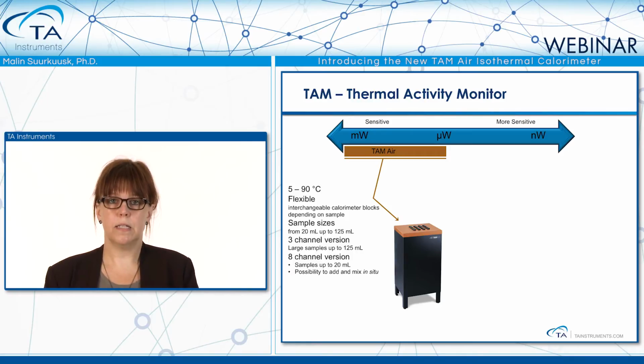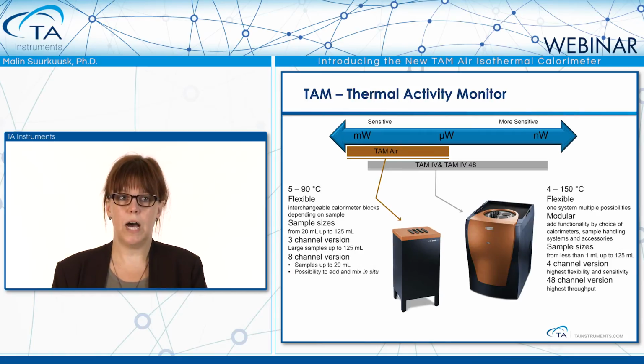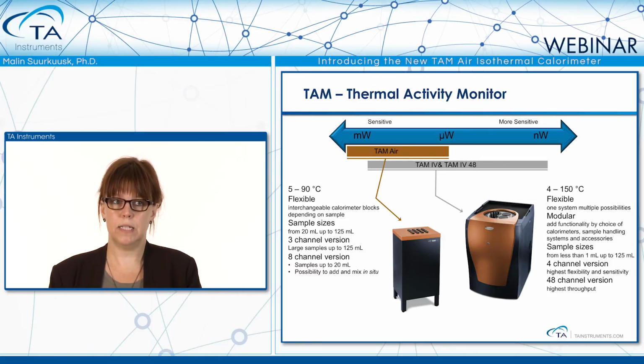But for some applications, the sensitivity of the TAM Air is not enough. Then we do also have the TAM 4. It's the more flexible calorimeter. It has much more sensitivity. It goes over the whole sensitivity range, back to nanowatt sensitivity. And this is a completely modular system that you can build up to your own needs, from very small samples below 1 milliliter up to 125 milliliter samples in this case. So depending on the needs, there is the TAM Air, which is perfect for cement and concrete and food applications. If more sensitivity is needed, there is also the TAM 4.